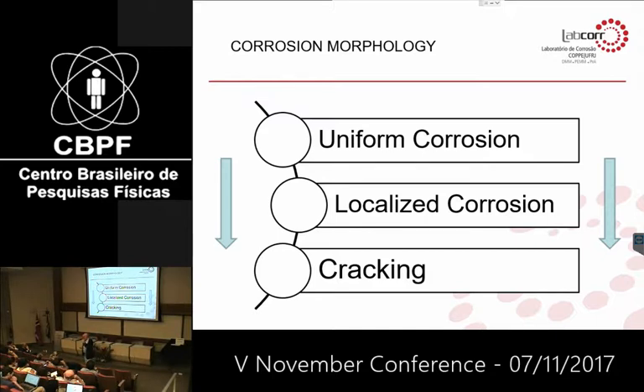The question is when the corrosion morphology is different. It moves from uniform to localized. And there are a lot of factors that can drive this morphology modification. The ingress of seawater is one of them, because with the seawater comes the chloride. And even the iron carbonate precipitation can be not homogeneous.